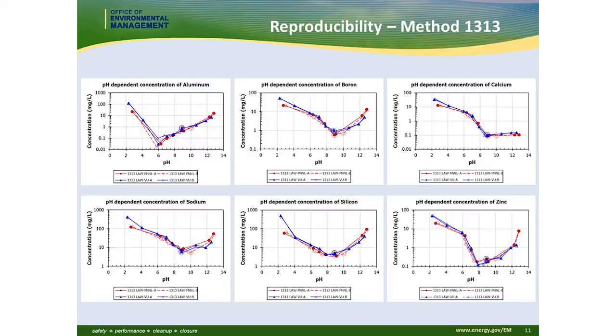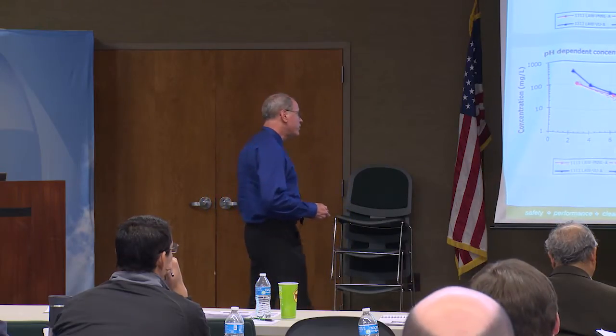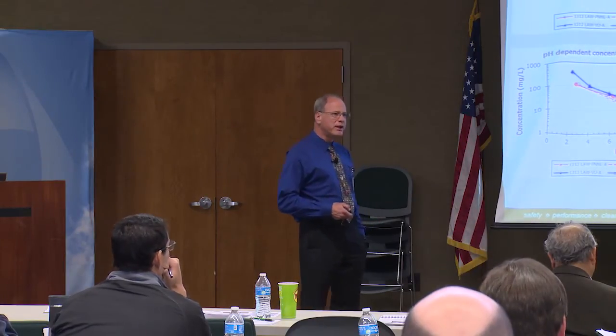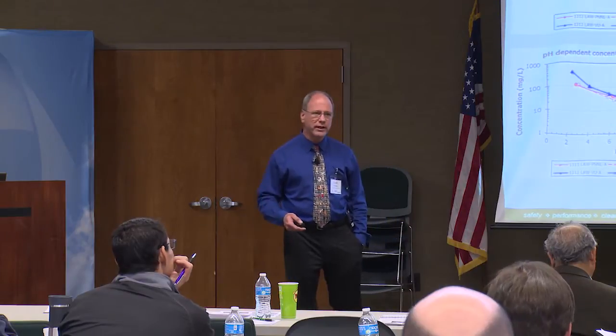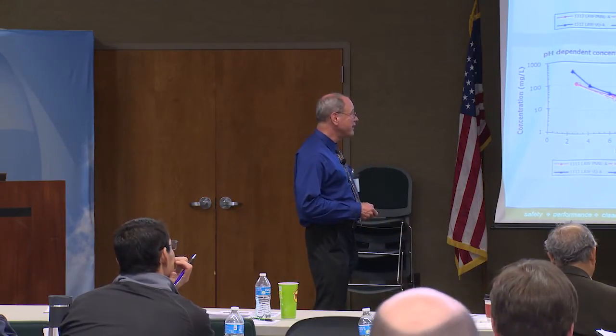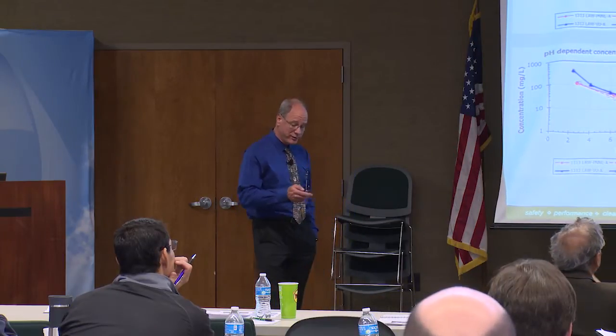But what you can see here is, when you look across several different elements that have different roles in the glass, ranging from the aluminum silicate, the boron, or the sodium, the fluxes, very good reproducibility, and also a very different characteristic behavior as a function of pH. It's important to recognize that the leaching behavior of these materials will be different if you're in an environment that has a pH of, say, 10 versus a pH of, say, 6 or 5, depending on what your actual disposal conditions are. So it brings to light the importance of pH on the leachability and degradation of glass. We tend to think about it being more degraded under very extreme alkali conditions, but tend not to focus on the sensitivity in the near neutral domain, which for some constituents is very sensitive.